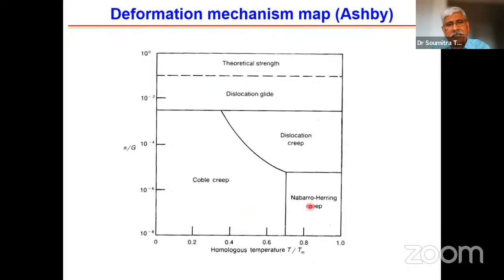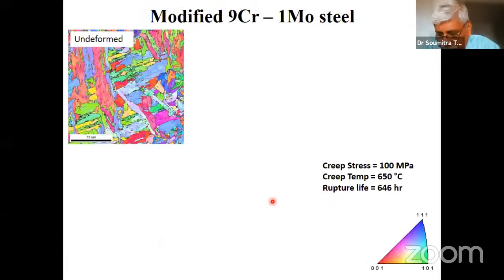Usually components and structures are at a very small sigma by G, and your homologous temperature is usually above 0.4. So you usually have a combination of these. And unless this progresses to a high damage level, the failure does not take place. So can you quantify what you have? But quantification separately in each of these mechanisms is impossible because concomitant with creep, often you have microstructural degradation at a high temperature. So we again use non-destructive, nonlinear ultrasonic, non-destructively.